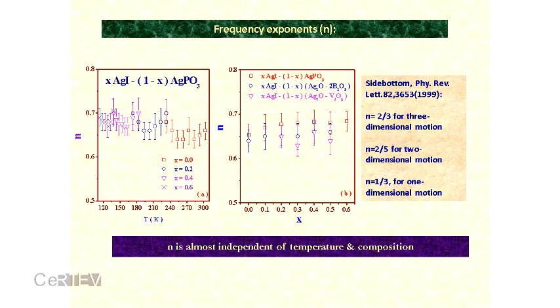One person predicted some value for the exponent. You can see he has shown that if the value of the exponent is 2/3, 0.66, then the conduction is 3 dimensional. And if it is 2/5, it is 2 dimensional, and as 1/3, it is 1 dimensional. So our value of 2/3 corresponds to 3 dimensional motion in these so-called super ionic glasses.